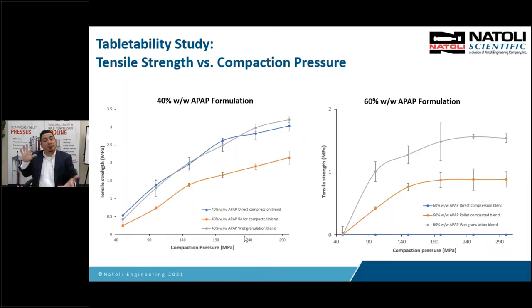Most tool maximum pressures, depending on the shape and if it's an exotic design and logos, you should be getting in the 500, 600 megapascal range before that tool fails. So that's all the way up to 500, 600 megapascal. But if you've got an exotic tool shape and different steel, that'll reduce the max force and you might be reducing that pressure maybe closer to 300. But anyway, here's our 40%. We achieved our 2 megapascal with the direct compression and wet granulation at relatively low pressure. The roller compacted blend took more pressure to achieve it.